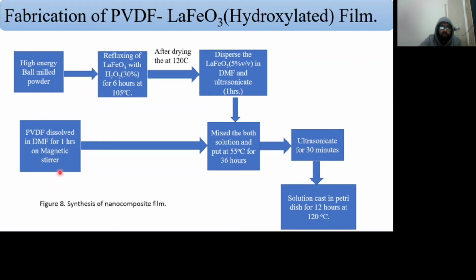Simultaneously, we dissolved the PVDF in DMF for 1 hour on a magnetic stirrer. Then both solutions are mixed and put at 55 degrees Celsius for 36 hours on a magnetic stirrer. After that we ultrasonicate for 30 minutes, and this paste was solution cast in a petri dish for 12 hours at 120 degrees Celsius.